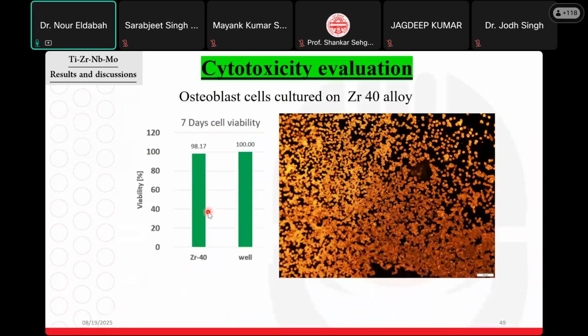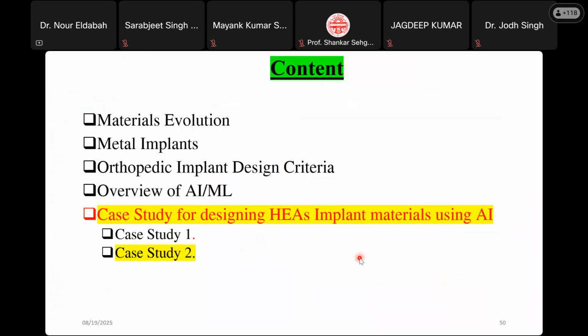We repeated the test, but in this case we used osteoblast cells, and these cells are responsible for building the human bone and will be in contact with the implant. We found very healthy cells on the surface of our alloy, especially the zirconium 40, with a viability reaching 98.17 percent when compared to the control well. Now I can go to the second case study if you have no questions.